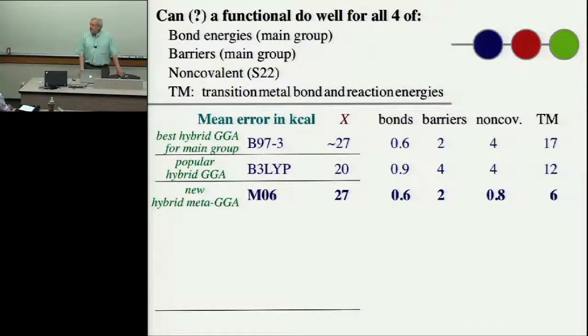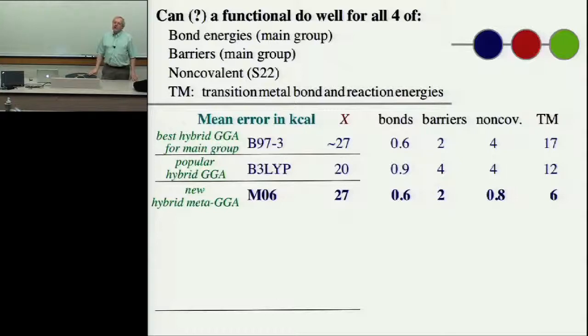With or without zero-point vibration? Yeah, that's my next question. Well, when we do tests, there's two ways to do tests of geometries. One is to calculate the potential surface and then put in the vibration, because it's anharmonic, the zero-point vibration shifts the lattice constants or the bond energies if it's a molecule. We tend to do it the other way. We tend to try to make the best possible estimate of how big that shift is and correct the experimental data to get the actual equilibrium structure, the place where the potential energy has a minimum, and then we do that comparison. But what we don't do is run the calculation without vibrational effects and compare to an experimental value that's influenced by those effects. We try to do it consistently one way or another. So when I talk about comparisons, they're consistent comparisons.